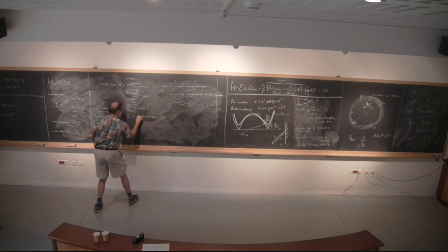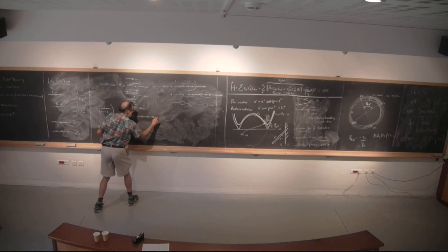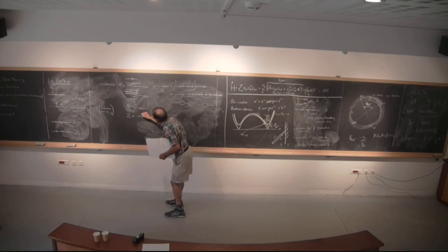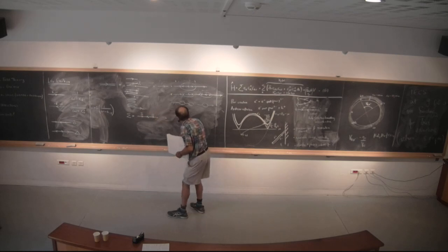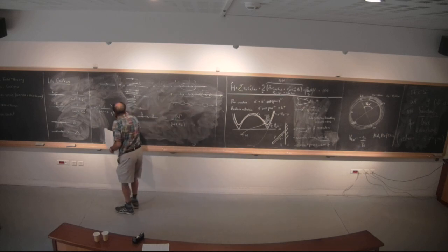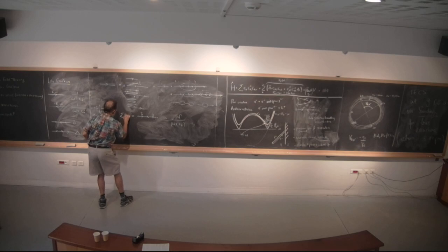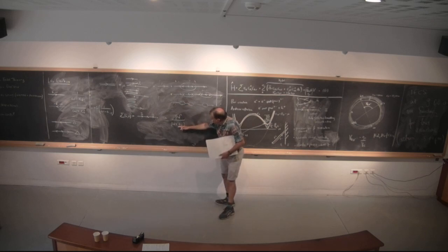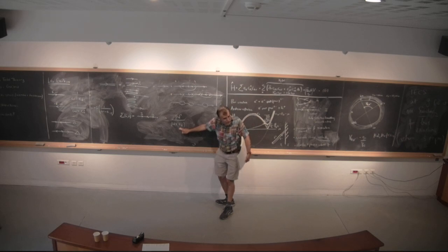It involves the electron coming in here, scattering, going back, and we give this an amplitude. It's just this one has a delta bar, this one has a delta. So it has amplitude mod delta squared over omega plus epsilon k. That is our self-energy. It's a function of k and omega. Okay? And notice this thing has a pole at omega equals minus epsilon k. So it keeps the information of the hole that's there in the middle.